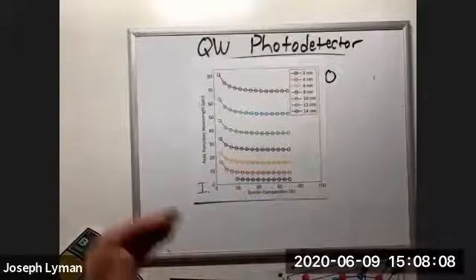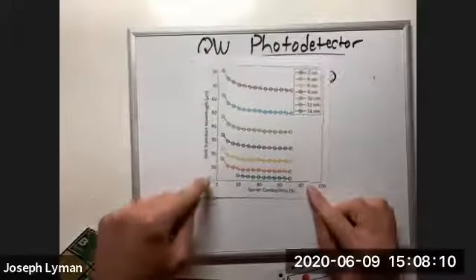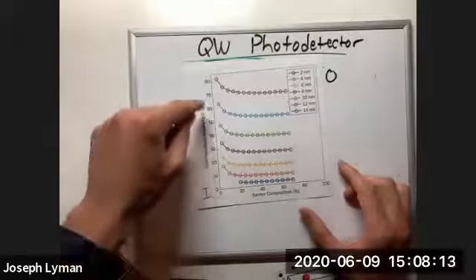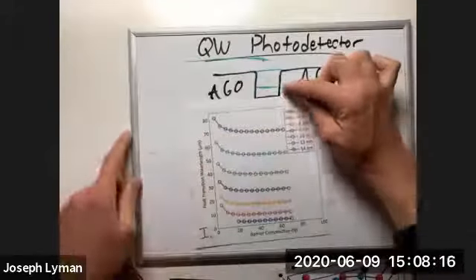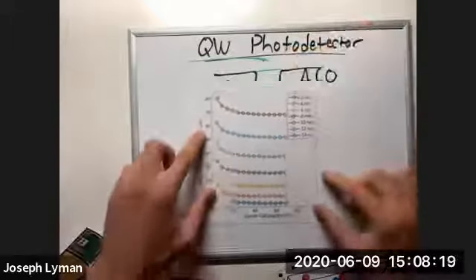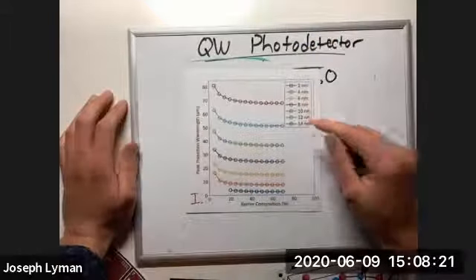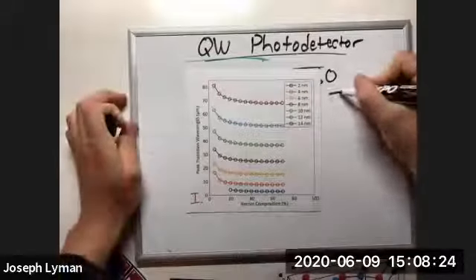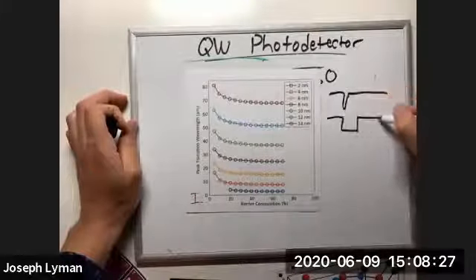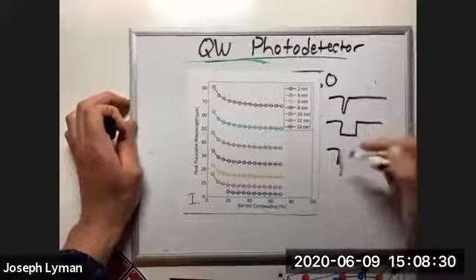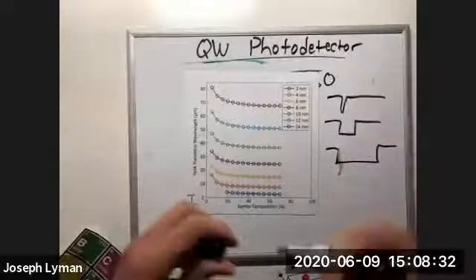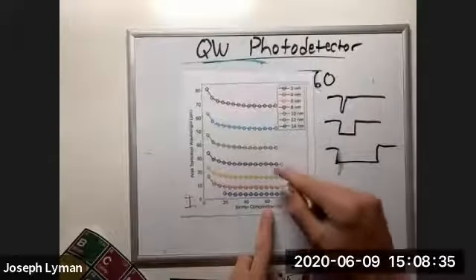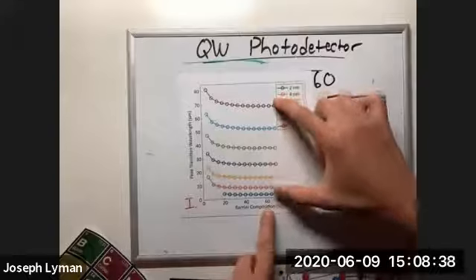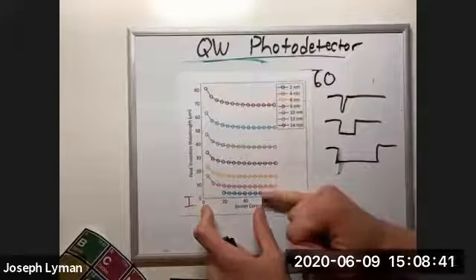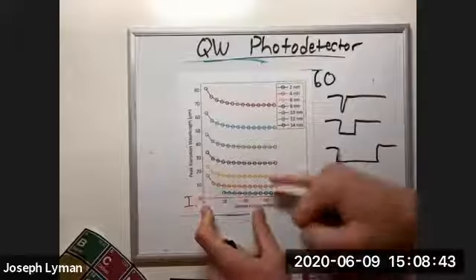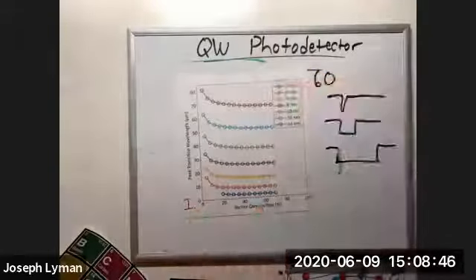So this is kind of a showcase of what wavelengths of light we can absorb through this process of excitation from the ground state to a higher state with different well widths, how wide the well is. This might be 2 nanometers. This might be 4 nanometers. This might be 14 nanometers. So we changed the well width, 2 nanometers, 4 nanometers, all the way up to 14 nanometers, and we were able to show that we could absorb wavelengths from about 1 micrometer to 70, maybe even 80 micrometers.